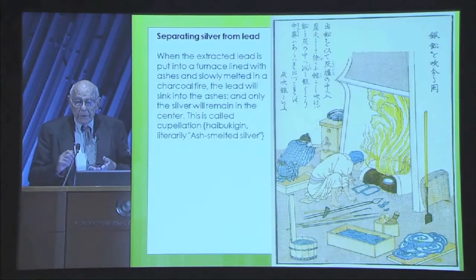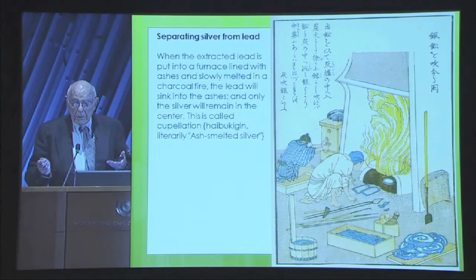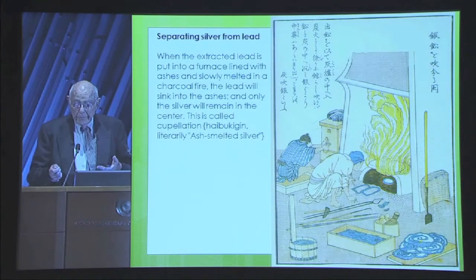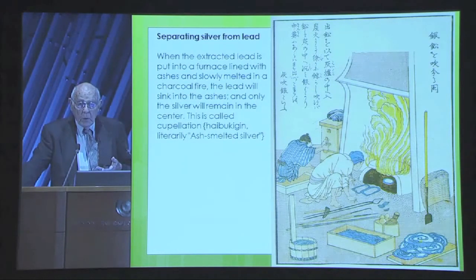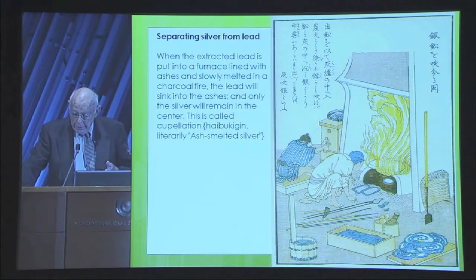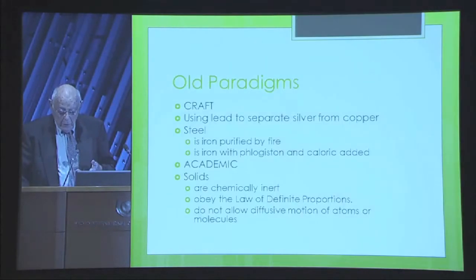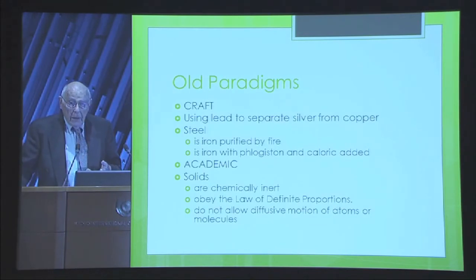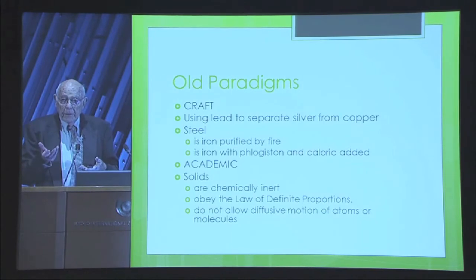But it made this enormous difference in the material. And as soon as people realized that that's how you made steel, they could control it better, they made better steel, they made it much more quickly. And in fact, they used the Chinese method where they added high carbon cast iron to steel. So here was an example of a revolution from a very simple experiment and a complete paradigm change in the sense that now we knew steel was not pure.